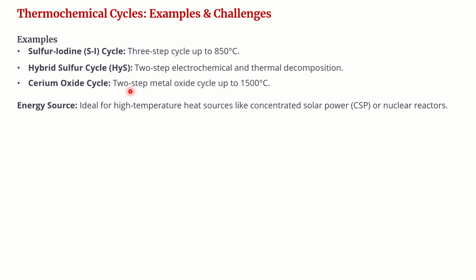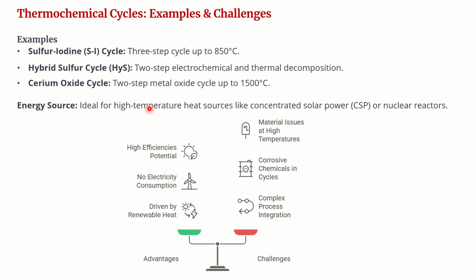In the cerium oxide cycle, a two-step metal oxide cycle using cerium oxide requires very high temperature, up to 1500 degrees Celsius, for the reduction step. The advantages of this method are that it is potentially high efficiency, and it can be driven by high temperature renewable heat sources. And what are the challenges involved? High temperature still poses some material challenges, there are corrosive chemicals in some cycles, and also complex process integration.